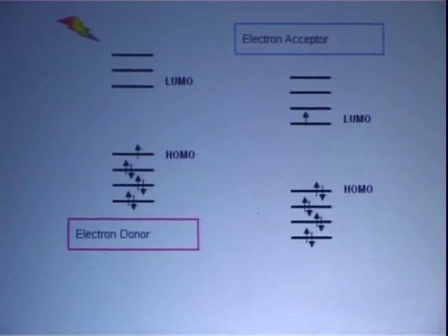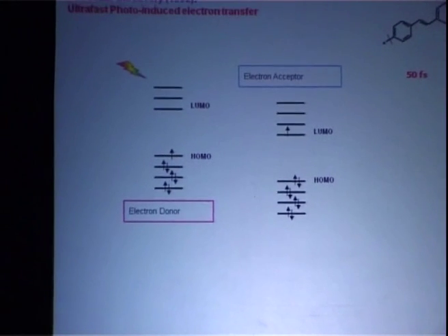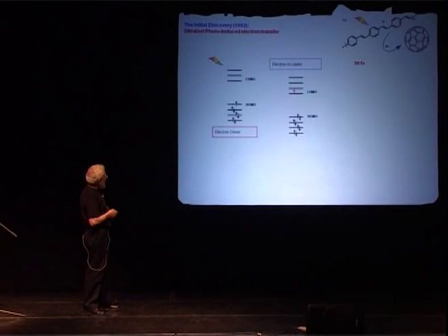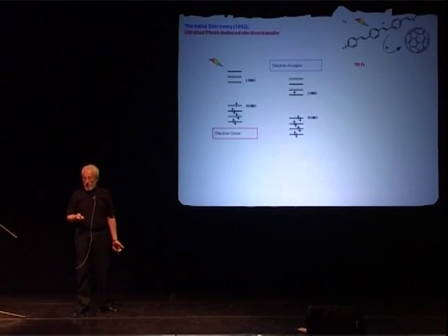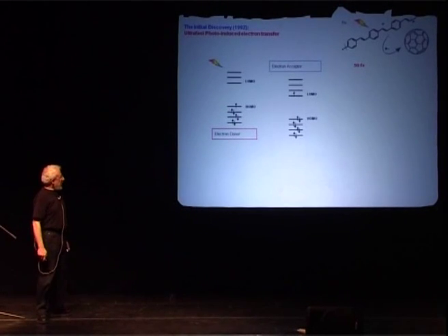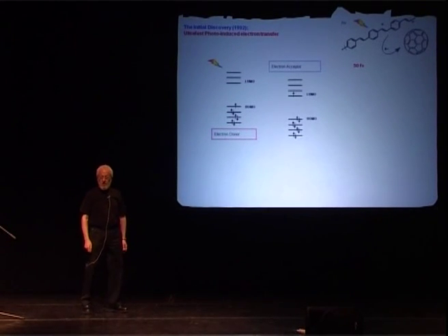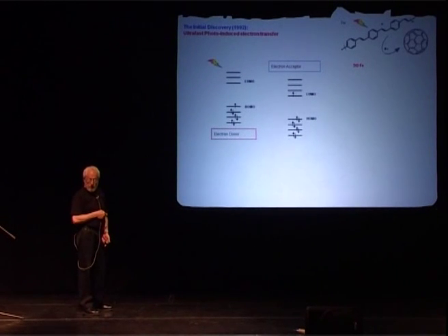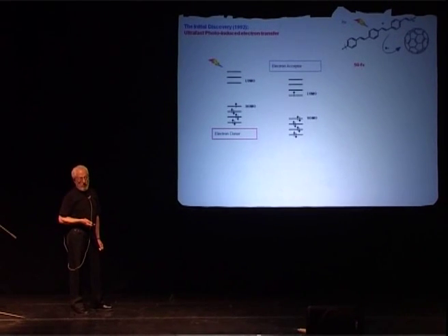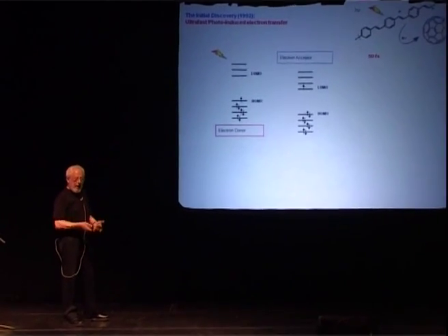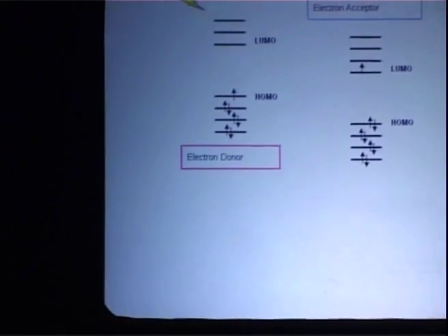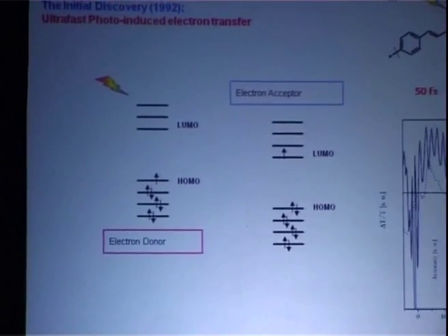So when the electron transfers, it gains energy, but the fundamental rule is you have to conserve energy. So you should ask, well, where did that energy go? And that's often, in charge transfer problems, a bottleneck. In this case, it's not, because when the electron transfers, the hole can kick to a higher energy, Coulomb interaction. There's no need to wait for a fluctuation of a phonon, whatever. So it is really fast. 50 femtoseconds. It's been time resolved.